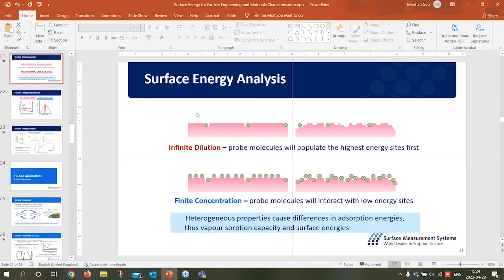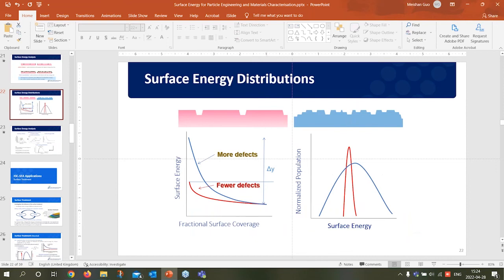So here we have the range for the high energy side and the low energy side. So in case of the high concentration of the probe molecule, there will be some other interaction between the probe molecules. So the solvent-solvent interaction is more dominant in this high range. And what we find out is below 20% of the coverage, the surface energy will gradually go to a plateau. So most of the energy profile will end at 20%. So even though you increase the concentration even further, it will still give you a very similar value as the low energy side. So it's not very necessary to increase that high surface energy coverage, but you can still do that, of course. But at high concentration sites, it's not that accurate because the solvent does not interact only with the solid itself. I hope that answers your question.